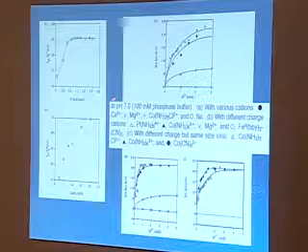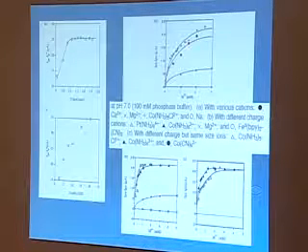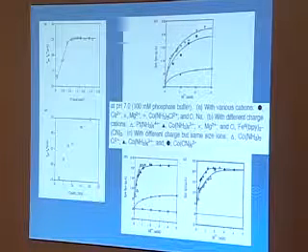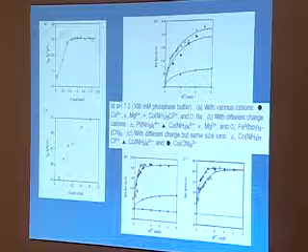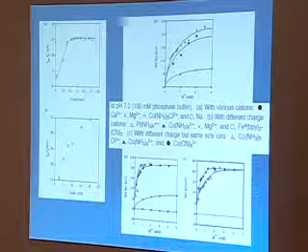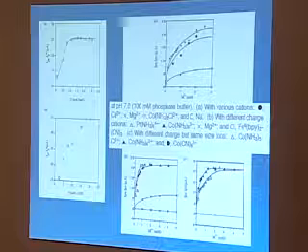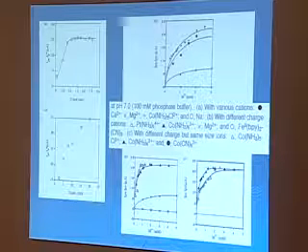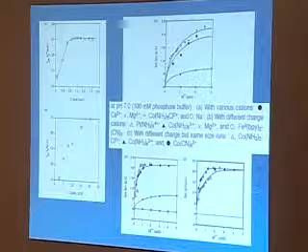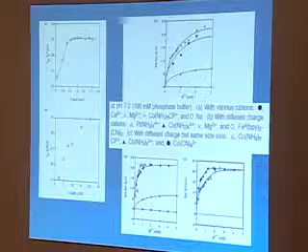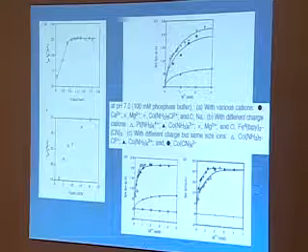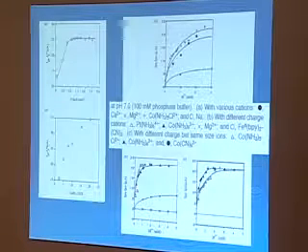So we look at calcium ions. Those are the black circles right there. They're quite nice. Magnesium ions are the pluses. They're similarly very nice. And then you can go to even more bizarre things like this cobalt pentaammine chloro complex, 2+, only because it's 2+. You notice there are little differences here, but they all fall on the same plot, more or less. They're not all that different. So 2+ cations are good to have around, and 1+ cations don't do a lot for you.